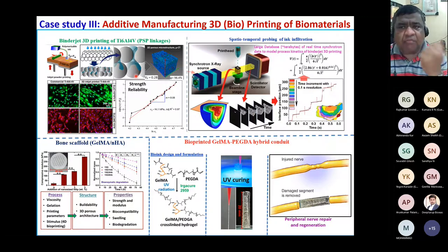And this we have done further using a synchrotron study at the Diamond Light Source in the UK in collaboration with Brian Derby's group at the University of Manchester. So what you see is, in a fraction of a second, how the interface position is changing with time, and that has been modeled using the established theoretical model. And then we have further developed a new modified model to fit our experimental data.